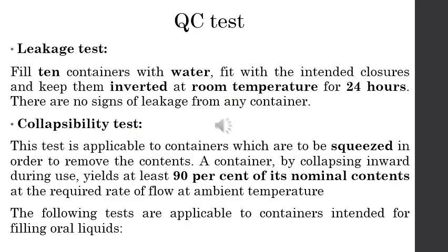Next we come to the QC tests of plastics. The first test is the leakage test. For this we randomly select 10 containers, fill them with water, and fit whatever closure is used. Then we keep them in an inverted position at room temperature for 24 hours. After 24 hours we check for any leakage from the container.